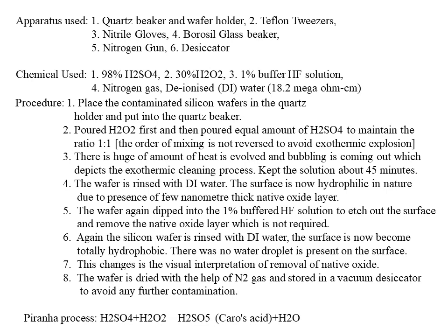The wafer holder holds the wafer and puts it in the quartz beaker, and after that we pour H2O2 and H2SO4. To hold the silicon wafer, we use Teflon tweezers, not any other tweezers made of SS material. For precaution, we are using nitrile gloves, and the borosilicate beaker here is just to hold the DI water.